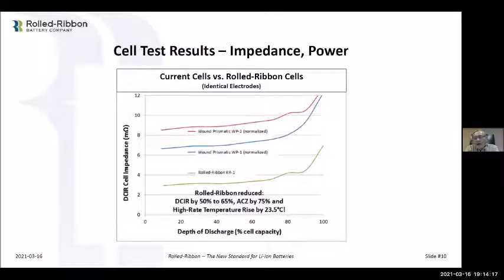Yeah, they're fused. Again, the electrodes are made exactly the same way they're made today. So for those not familiar, when you make a lithium-ion electrode for lithium-ion cells, they take the active ingredient, whatever it is, lithium iron phosphate or lithium cobalt oxide, and they create a slurry out of that, which usually includes binder, which is what binds it all together and sticks it to the foil. And then they coat it on there as a slurry, with a certain viscosity when you apply it. And then it goes through a baking process. They put solvent in there, which creates the slurry, and then they extract the solvent through the drying process. And so that's how the material gets coated, or sort of pasted, to the foil.